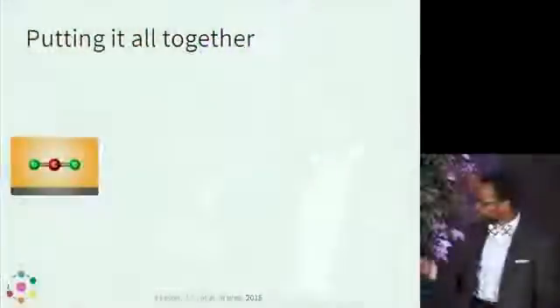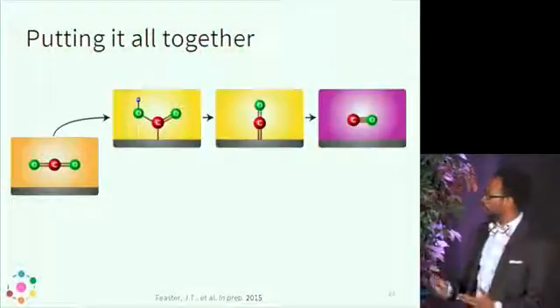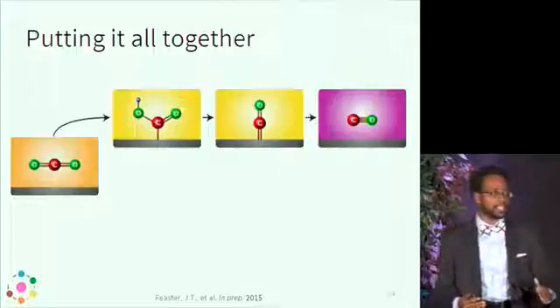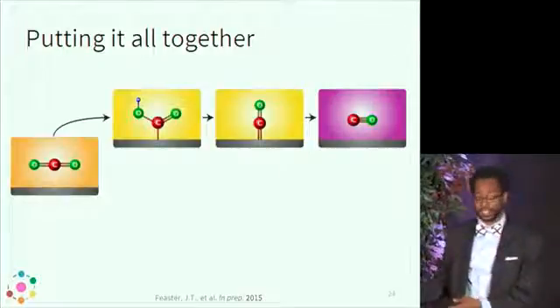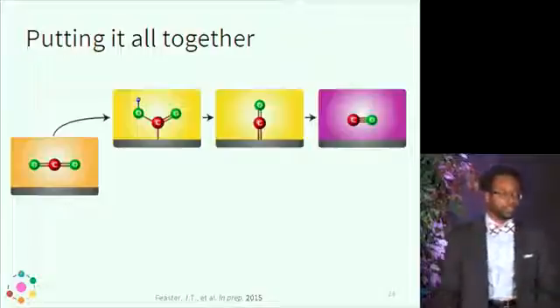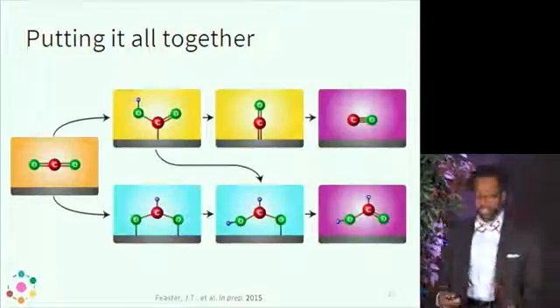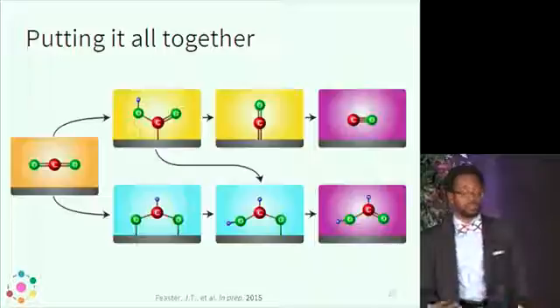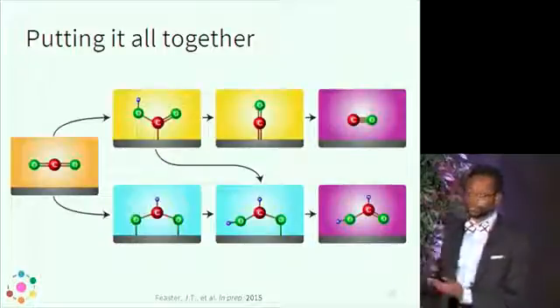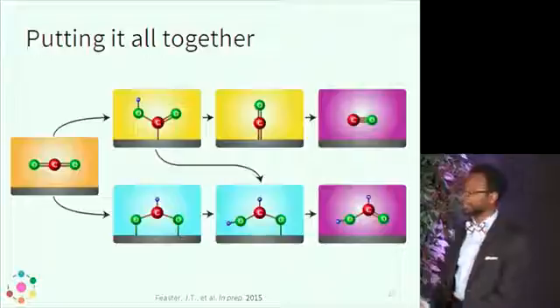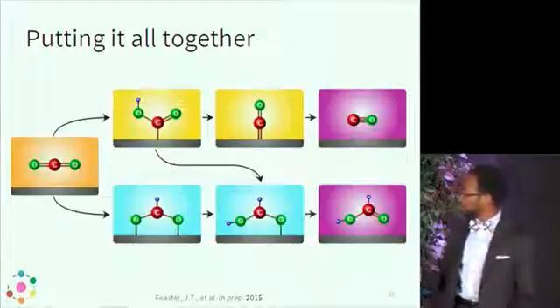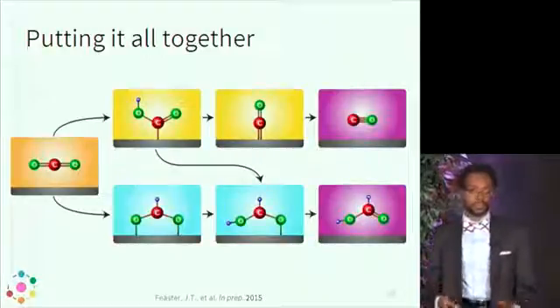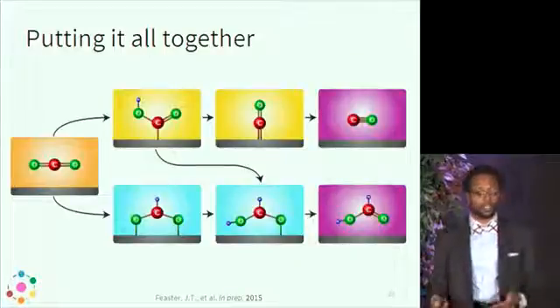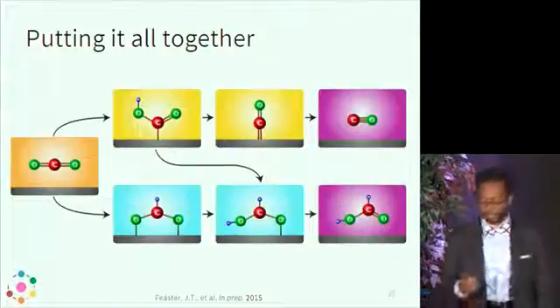And so to try to put this all together in terms of a pathway, if we start from CO2, we have the initial carboxylic acid type intermediate on the surface that leads to carbon monoxide, which many people in the field are very comfortable with. But then also, there's an additional pathway of oxygen binding to the surface for tin and for some of these other metals that results in formic acid being the major product. And as a result, it seems like this OCHO type intermediate on the surface is one of the key intermediates to determining what your activity for formic acid will be for CO2 reduction.